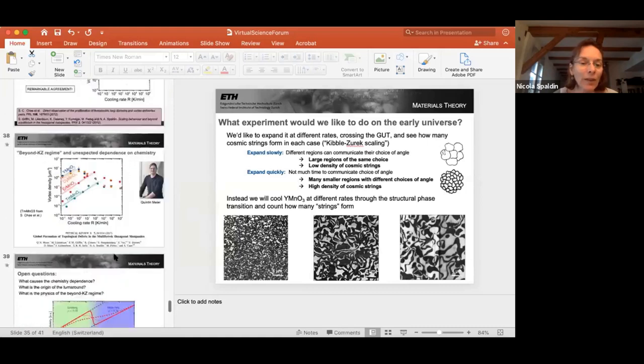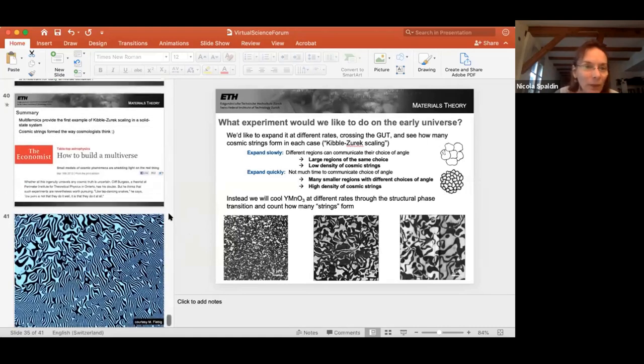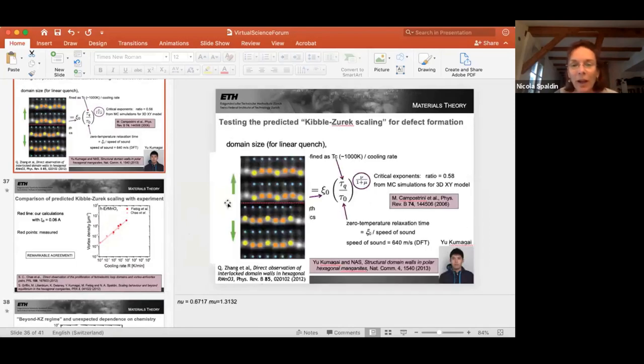One thing that is very interesting is, if I go back to this picture maybe, domain walls like this that are cutting perpendicular to the polarization, they create a polar discontinuity, are extremely unusual in conventional ferroelectrics because there's a divergence of the electrostatic potential at the domain wall. And here they form because of the topological protection, because the polarization emerges as a secondary order parameter. And so they lead separately to all kinds of interesting physics, like very narrow conducting channels. Which is a little bit of an aside. So I agree completely. It's really surprising that it's actually not very anisotropic, the domain structure.